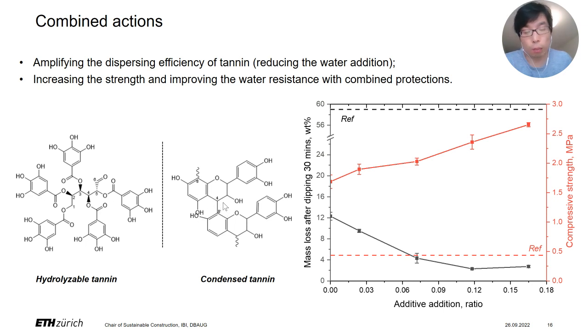So for sure, we can employ other modification of the tannin first to increase the dispersing efficiency. In that case, we can further reduce the water addition, and of course, by this combining action, we can further increase the strength, and most importantly, we can improve the water resistance of the sample here, like here.